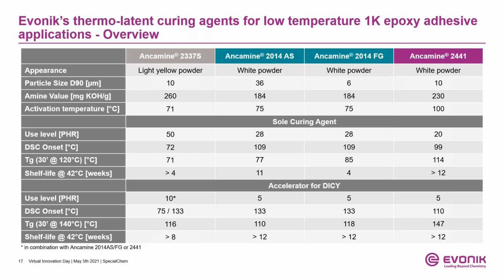As also indicated here, the potential activation temperatures range from around 70 centigrade for Ancamine 2337S up to 100 centigrade for the Ancamine 2441. To get a more detailed impression on the potential of the modified aliphatic amines when used as sole curing agents or as accelerator for dicyandiamide, we will now go through some experimental results on basis of simple model formulations with a special regard on reactivity, shelf life, thermal stability, and lap shear strengths.